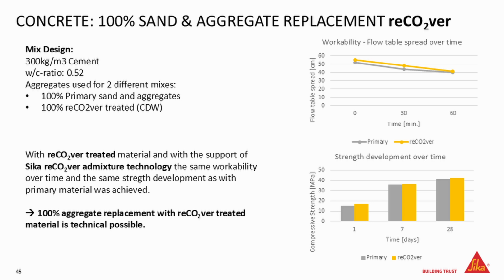So what we did is we developed admixtures for both, because the workability issue, especially the slump keeping issue over time, cannot be covered by conventional admixtures at the moment. So there we had to bring new technologies, and we strongly believe that the key for the future is an accelerator, a special type of accelerator that we use for these recycling materials, because this is where we see the trends.